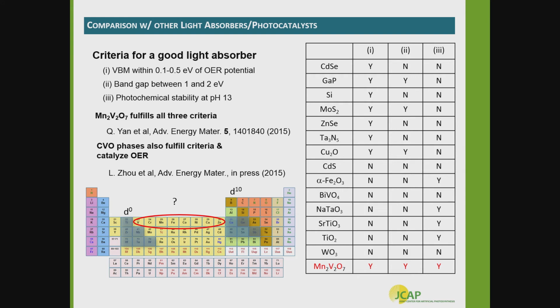And so among all of these criteria for having a good light absorber with an optimal band gap, favorable band alignment, and photoelectrochemical stability, manganese vanadate looks like an interesting case. And there are, of course, many others in these ternary alloy compositions of vanadium oxides that are potentially also attractive components to pursue, and that's underway.